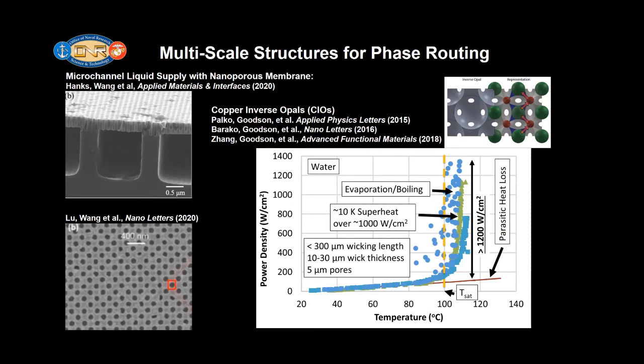And we were able to get to 1.2 kilowatts per centimeter squared with a very modest temperature rise through very aggressive convection. This shows a nice image of some of these inverse opals, and we can control the neck dimensions as well as the diameters of the pores, et cetera.